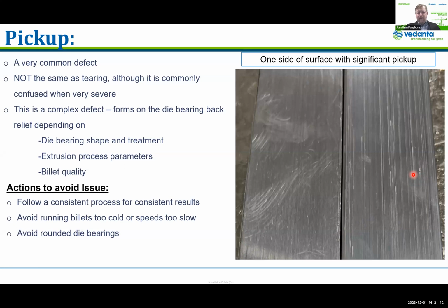Some of the factors that we look at when we have these problems are with the die, primarily, looking at the shape of the bearing, making sure that it's the correct shape, that it hasn't been rounded, that your die bearing angles are controlled, and then also your treatment of it, specifically for most products, it's going to be a nitriding. There are other coating technologies, but usually it's nitriding your tool steel and making sure you have a very hard, resilient layer. Extrusion process parameters also will have an effect, but not necessarily in a controlled or predictable way. I would say usually higher temperatures and sometimes faster is better, but that's not a bulletproof solution, because as you're changing those parameters, you're changing the shape of the die in subtle manners, the way it is deflecting, how the metal is coming off the die bearing. There can be billet quality issues, so that's at least something to be cognizant of.